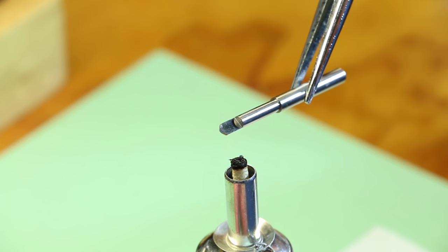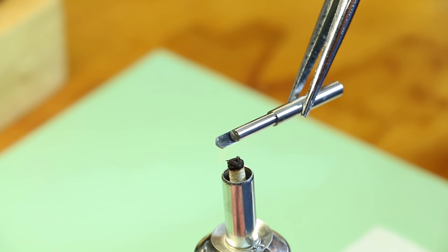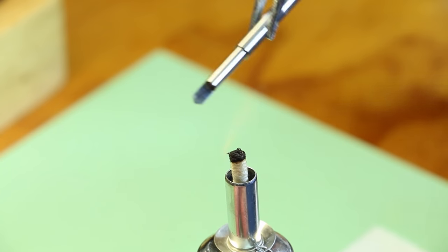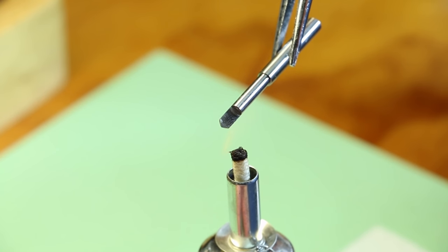Don't put the tip directly in the flame as it's only small, you will temper this part before the rest of the tool and end up making the tip too soft. I must apologize, I did change camera positions to get a better visual for the color change and I actually forgot to hit that record button.